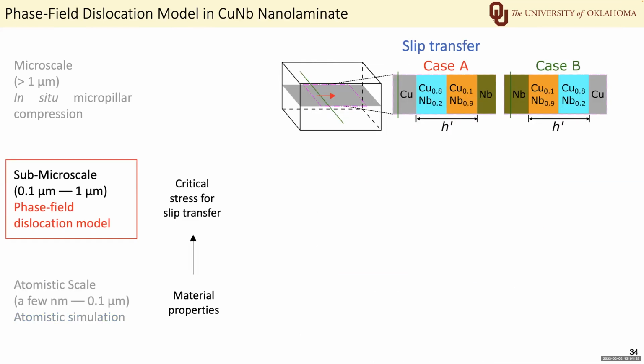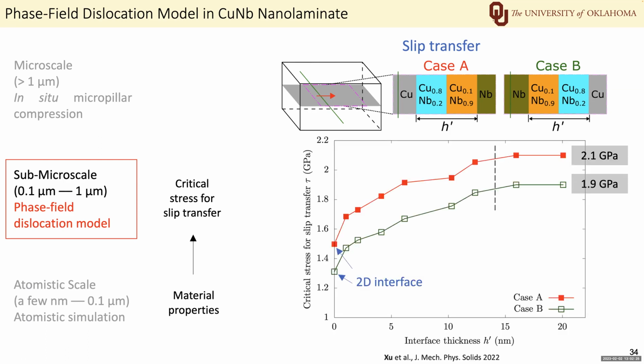Then I use the phase field dislocation model to study the slip transfer of dislocation across the 3D interface. This problem is very important because the slip transfer process controls the yield stress of the laminate. I considered two cases. In case A, the dislocation is initiated in copper and ends in niobium. In case B, it is the other way around. In each case, I vary the interface thickness from about 1 nanometer to 20 nanometers.